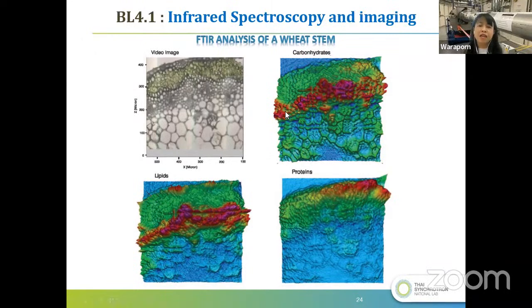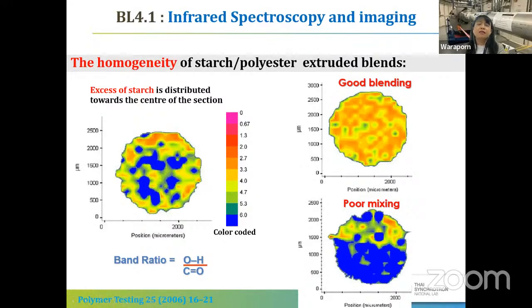So we can see that the carbohydrate is localized at the vascular bundle, and also the lipid CH, CH2, CH3 groups and C double bond O group all together. We can see the localization of lipids at the vascular bundle as well, but not for protein, which is very close to the epidermis. And if you have a polymer blend, for this one a starch and polyester blend, we can see whether the blend is good blending or poor blending by using the ratio of OH and C double bond O. So if it is good blending, the color of the analysis will be like this.